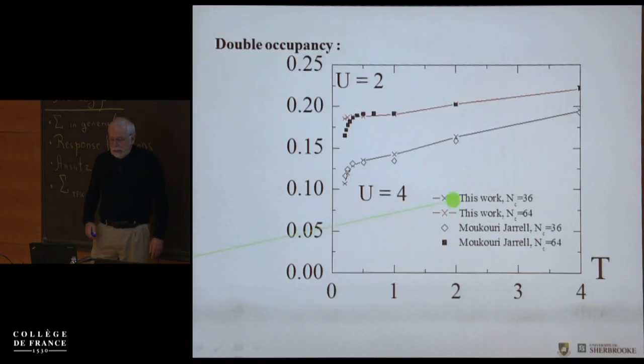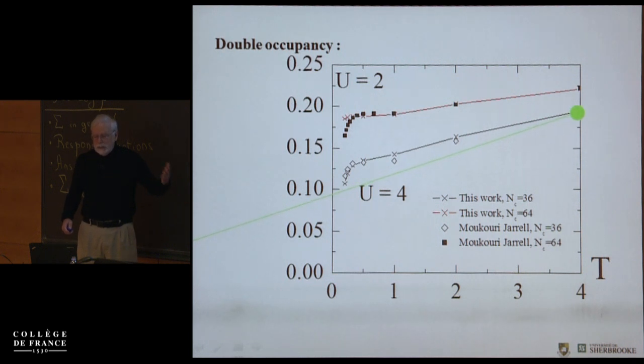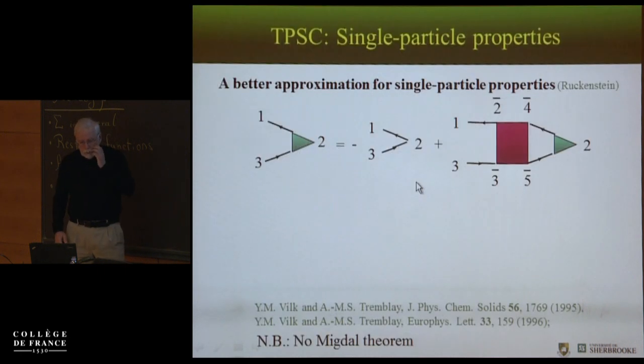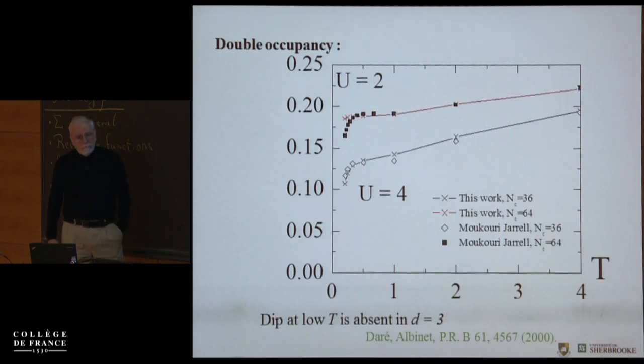This is comparison with DCA. So we are comparing now a method that's good at strong coupling with a method that's good at weak coupling. And at U equals 4, the DCA calculations are the open symbols, and TPSC is the crosses with the line. One should emphasize that since this is a relatively small U, when the correlation length is large, one needs to go to large clusters to get these good results. Yes, you see it was 64, 36.